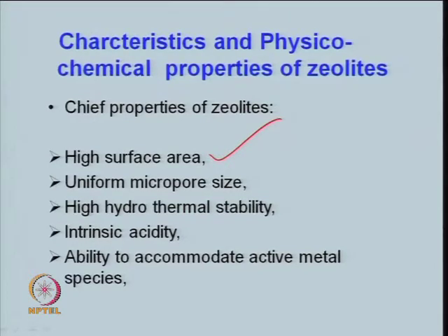Unlike your other commercial catalysts like alumina, silica, ceria, zirconia, they may have a wider pore size distribution, right. Depending upon your sintering and calcination conditions, sintering may take place, or at high temperature a solid-solid reaction. So, their pore size may vary in a wide range, but in the case of zeolites, the nuclei which form and the crystals which develop during your hydrothermal synthesis are very important, and depending upon the framework of that zeolite, their pore openings are in a narrower size range, right, because it is a kind of definite